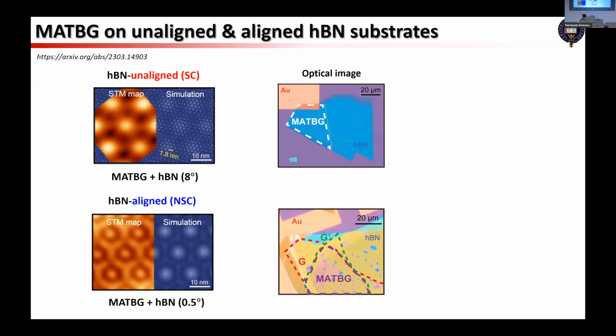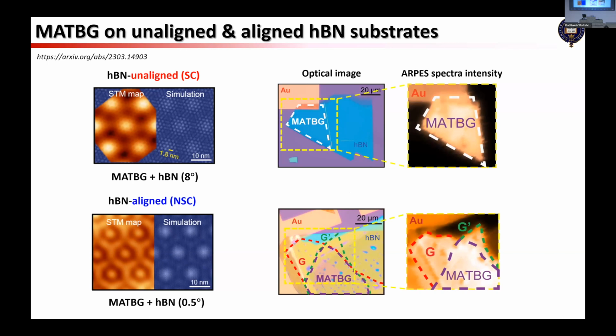And here are the geometries of the two samples. Although you probably cannot see this MATBG on top of the HBN very clearly because it has very low optical contrast, for ARPES, on the other hand, we have good news, because we can clearly see the difference between a conductor and an insulator. So here is the ARPES spectral intensity. We can clearly see the MATBG region, while the HBN, which is clear in the optical microscope, doesn't contribute any electron density at the Fermi level. So we were able to identify the MATBG region, and the same thing happens for the HBN aligned sample. Therefore we can choose a specific spot on the MATBG to study its band structure.